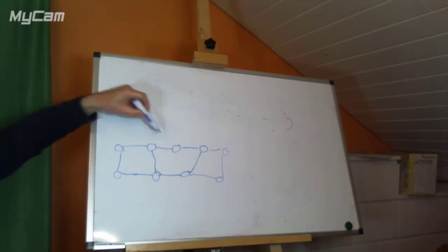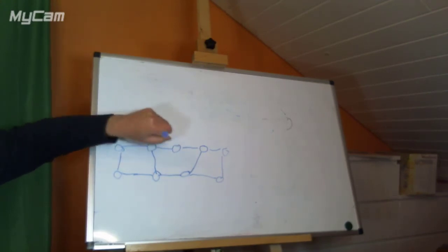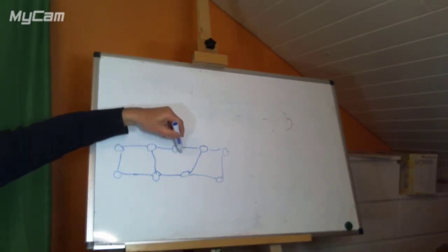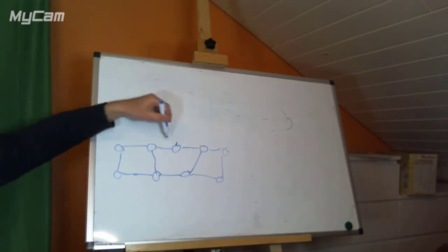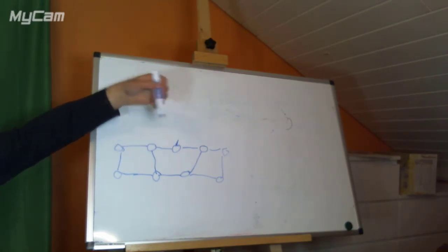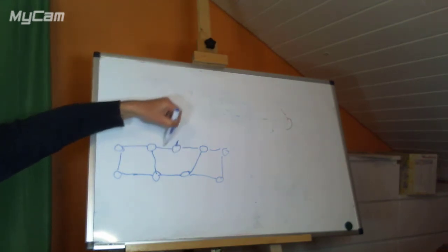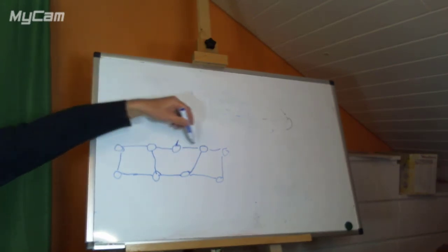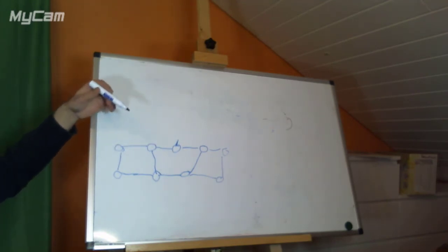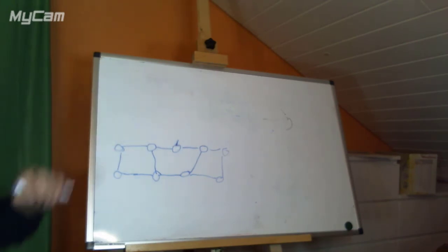In this case we've got a defect where this atom here doesn't have a friend below it. It would have one in the other dimension, but it wouldn't have one below it, and that will make this site higher in energy. This atom has extra bonding electrons that it can use to attach to things, and so that enables the next layer to form more easily. Or if we're dissolving it, as you know, this atom is obviously a target because it's not as well held in as the others. And these can then rearrange to form a more perfect crystal, but usually they are also starting to be removed at that point.